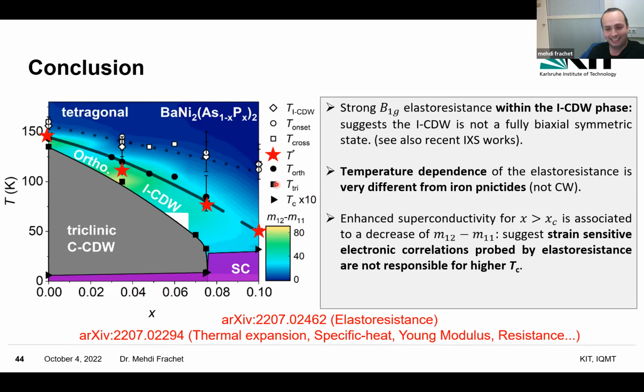He's the expert. Mehdi knows the answer, of course, but I can comment on that because we've been looking at this very closely. What happens is that you do have the CDW fluctuations, which are fairly short range from room temperature, and the correlation length increases as you decrease the temperature. Then you see the long range CDW order that forms just at the temperature which is just above that at which the orthorhombic transition is seen.